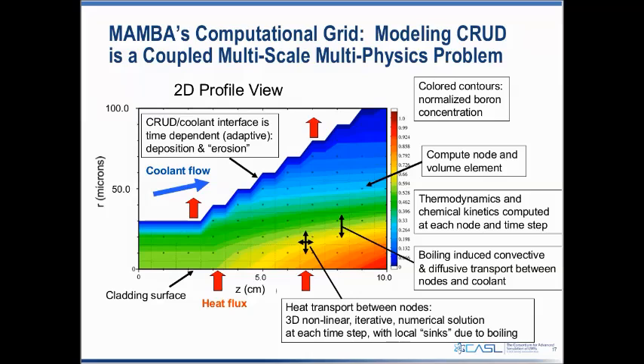We also have erosion effects occurring due to the turbulent nature of the coolant flow around the spacer grids, for example, and I'll talk more about that later. In order to compute the chemistry of CRUD deposition, we need to solve a heat transfer equation, so we need the heat flux at the cladding surface, depicted by the red arrows at the bottom, and the heat flux leaving the surface of the CRUD, depicted by the red arrows on top. Once we solve the heat transfer equation we get the temperature distribution through the CRUD layer.